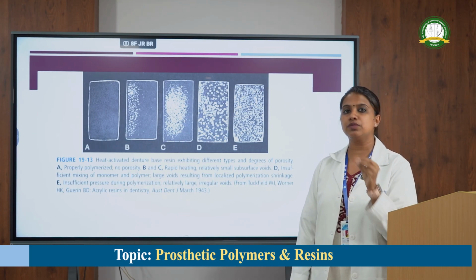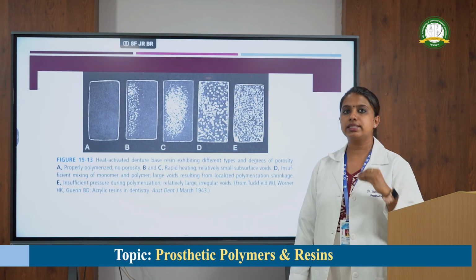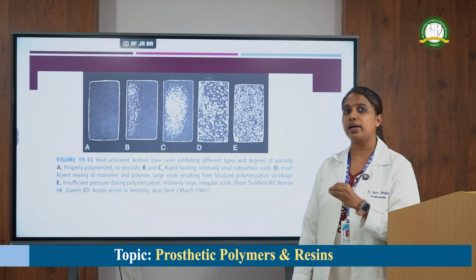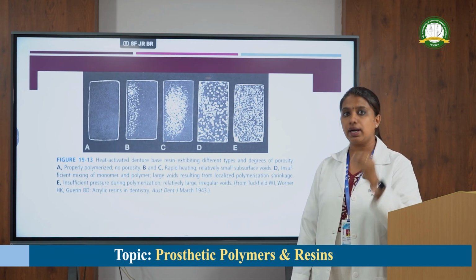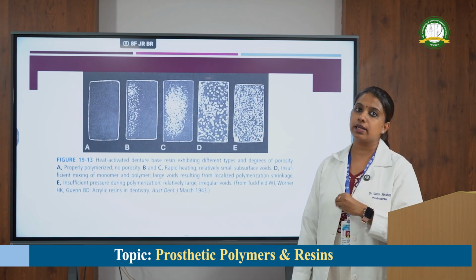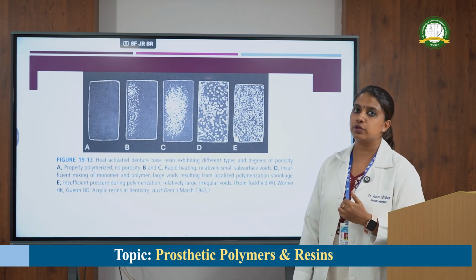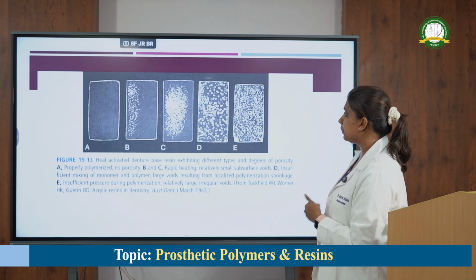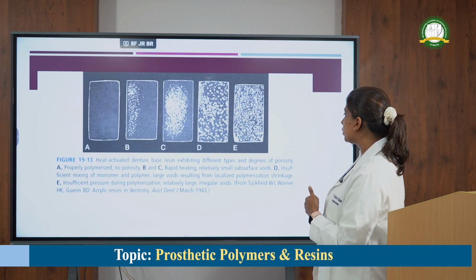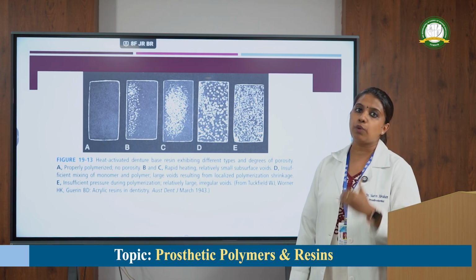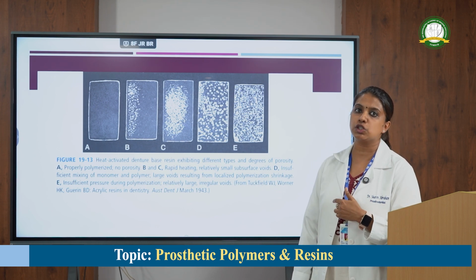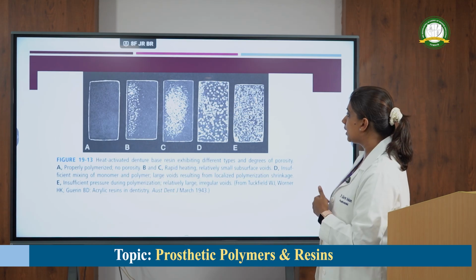There is a particular temperature range for polymerization of heat cured resin. It starts from 74 degrees Celsius to 100 degrees Celsius. If you go beyond 100, that is the boiling point, it can lead to small subsurface porosities, just like in pictures B and C. Now, in picture D, the porosity is mainly because of improper polymer to monomer ratio. The 3:1 ratio was not followed here, so you can see some irregular porosities.